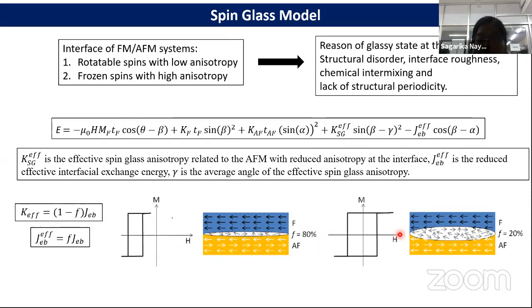In the two pictures, on the right side we see that the interface is completely disordered. When the interface is completely disordered, we get a symmetric loop. However, when the interface is a little bit disordered, containing both rotatable spins and frozen spins, this model says that there is a shift in the loop and you get exchange bias.